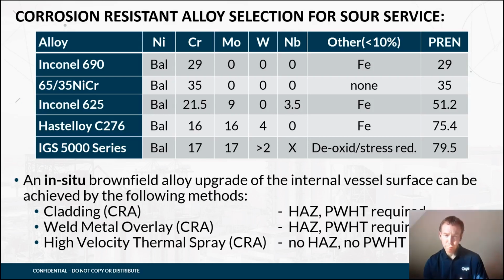As we talked about, we've got a couple of options in terms of cladding, field weld overlay. Both these options create these heat affected zones and require post-weld heat treatment, which can often be a very lengthy procedure, particularly when we're talking about large columns or vessels like amine columns. High velocity thermal spray is a potential solution. No heat affected zone, no post-weld heat treatment. However, high velocity thermal spray has to be the right class of technology to perform in these aggressive corrosive environments.